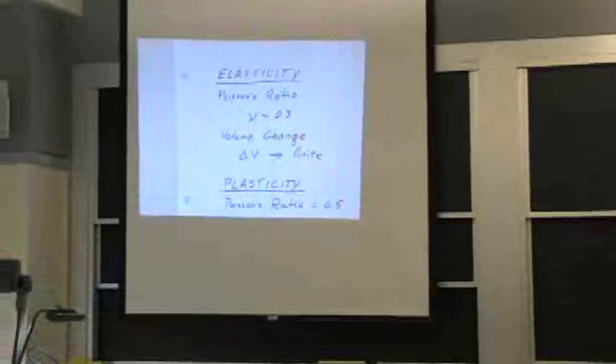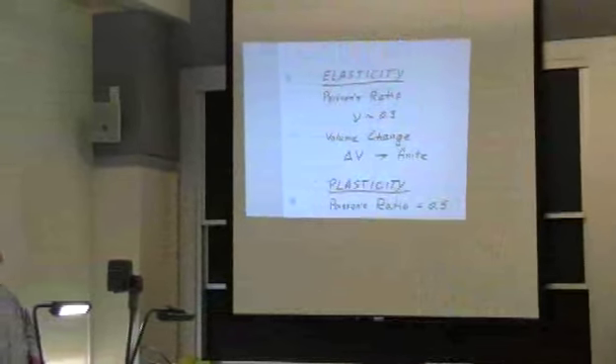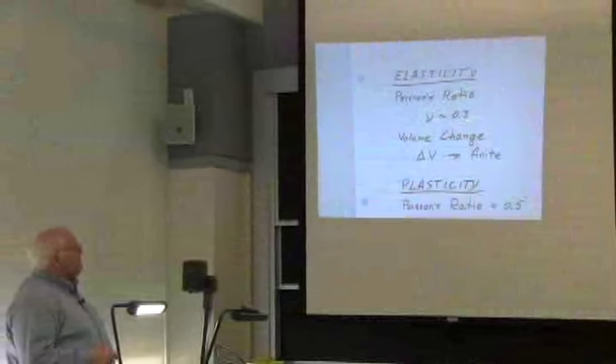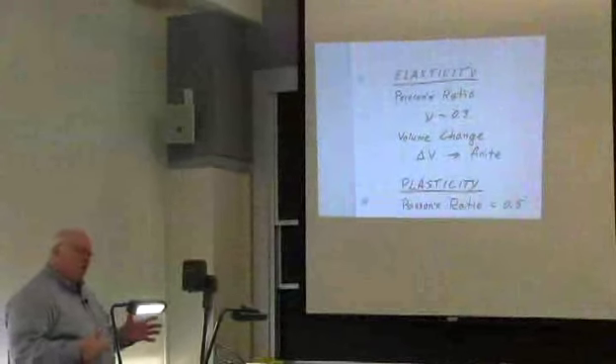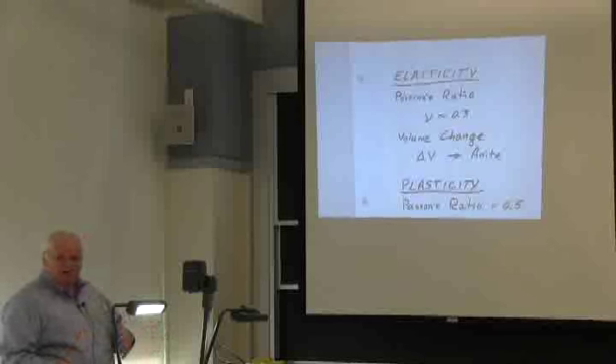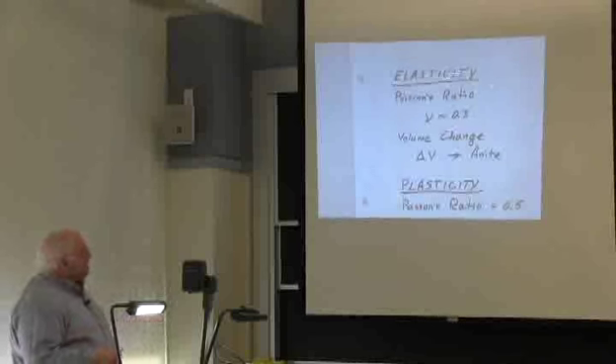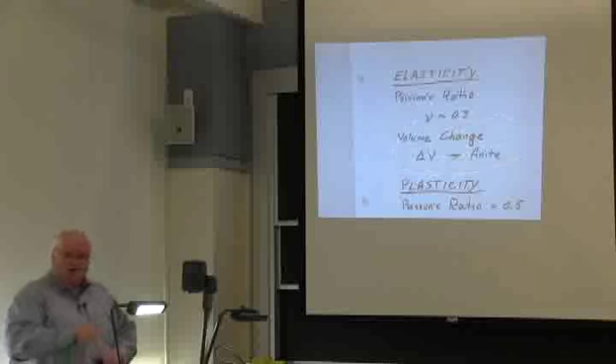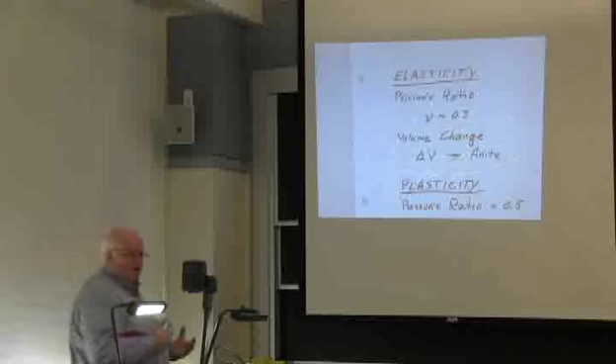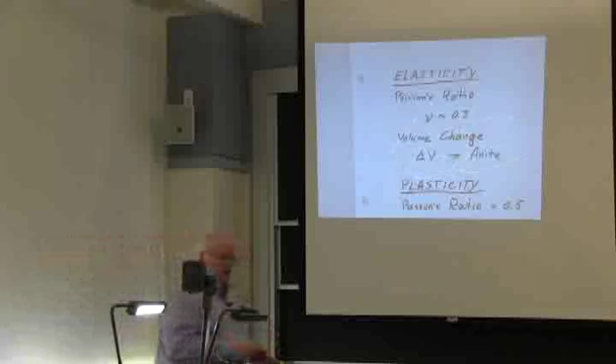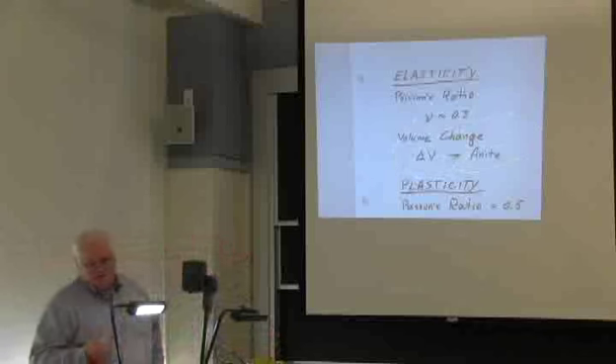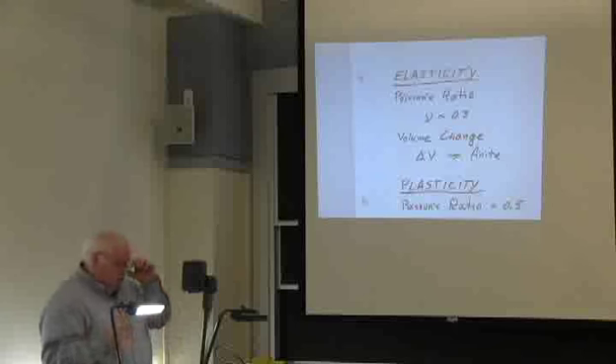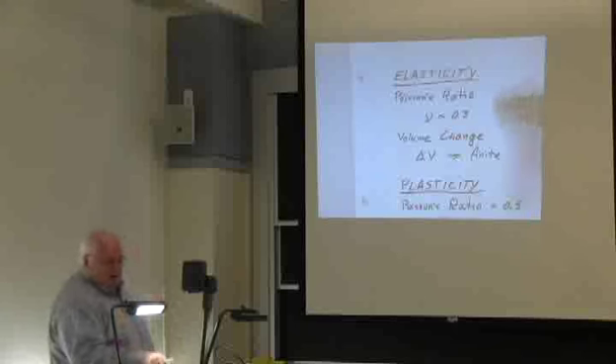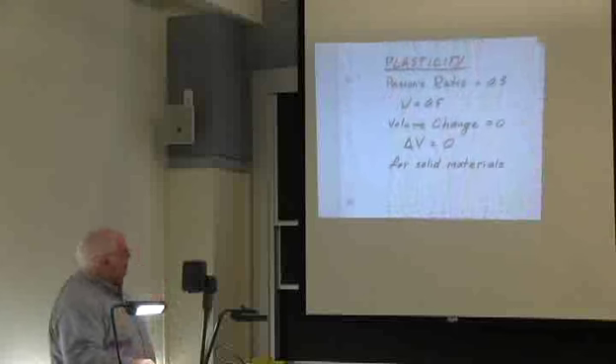And Poisson's ratio for a metal, a solid metal, is something on the order of 0.3. It might be 0.25, it might be 0.35. You can go look up in handbooks what the Poisson's ratio is for a given metal. Okay, elastic behavior. The volume change, if I pull on it, is finite. Now I can't tell you exactly what it is. There are formulas. It's actually the strain 1 plus strain 2 plus strain 3. But because Poisson's ratio is not a half, there is a finite volume change.